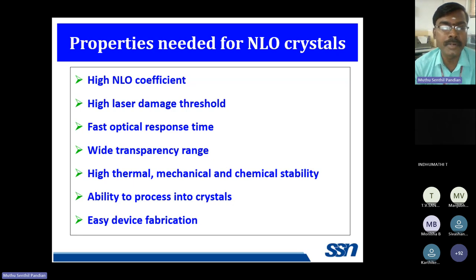Before we go for the actual large size single crystal, physical properties measurement, and crystalline perfection measurement for actual practical device application, we must ensure all the physical properties and the crystalline perfection of the grown crystal should be high: high nonlinear optical coefficient. For laser application, one must know the laser damage threshold value of the grown crystal. So we have carried out the single and multi-shot laser damage threshold for the SCST and SR method grown crystal, and fast optical response time, wide transparency range in the UV, visible and IR region.